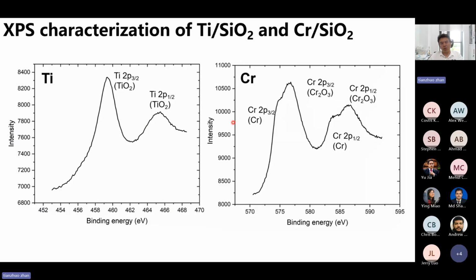And so we also did some XPS characterization of the titanium and chromium samples. We found that all the titanium was oxidized, and for the chromium, only part of the chromium was oxidized. So this oxidation of titanium may facilitate the heat transport between different layers.